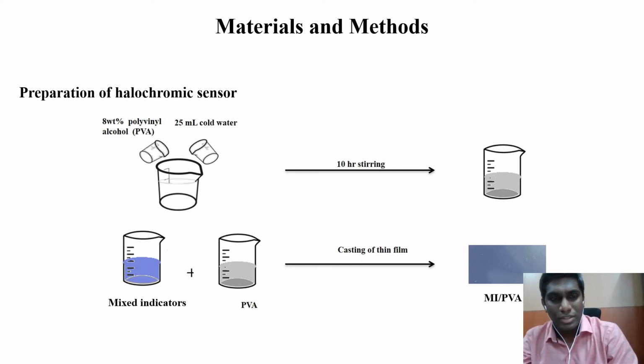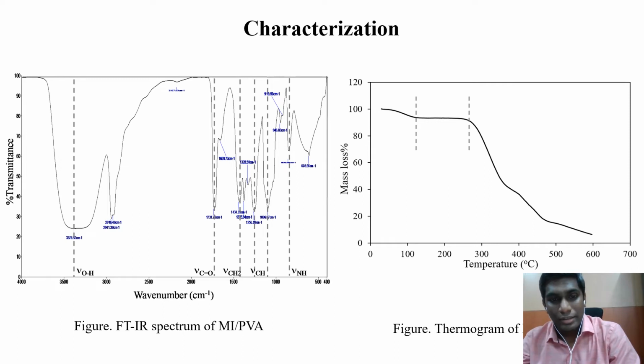Materials and method. We started with preparing the halochromic sensor, MIPVA, using the mixed indicator that consists of bromocresol green, bromocresol purple, bromothymol blue, and others, in total 7 color changing indicators. We mix them together with optimized concentrations. Then we cast it into a thin film by adding PVA. And this thin film was checked with the FTIR spectroscopy and TGA thermogravimetric analysis.